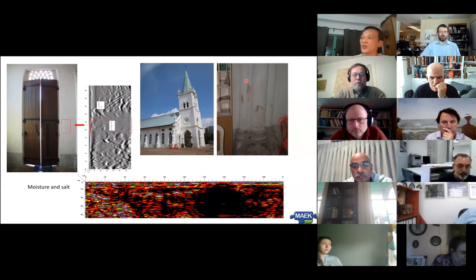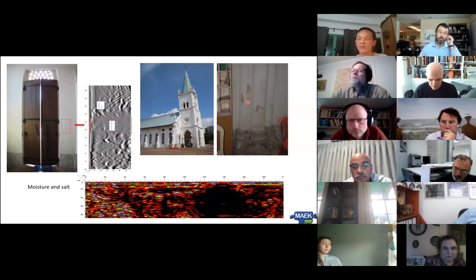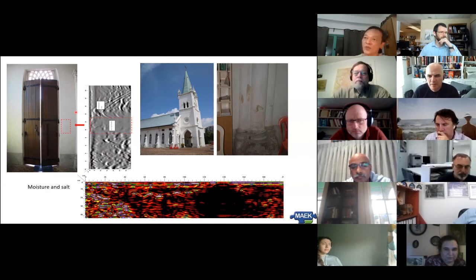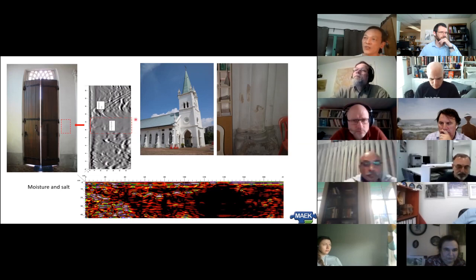But we couldn't find the salt content, which required drilling of powder and carrying out chemical analysis. So what we did, interestingly, was to run a radar from the bottom to the top. At a certain height, which appeared to coincide with the area where the salt has caused damages to the plaster, there is an attenuation of signal, which means the electromagnetic signals have been fully absorbed by the salt. You can see from here, it's about 1.2 to about 1.4 meter height.